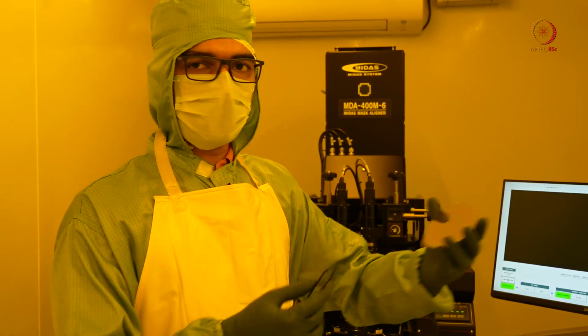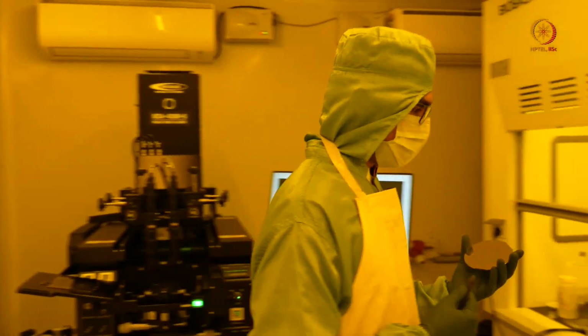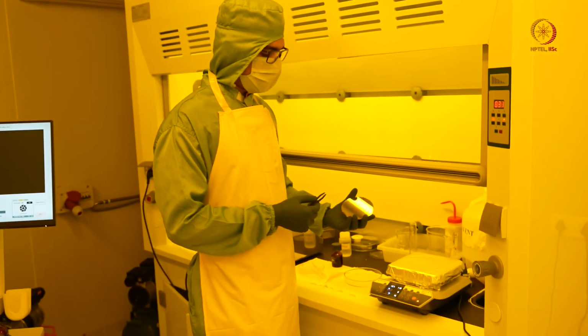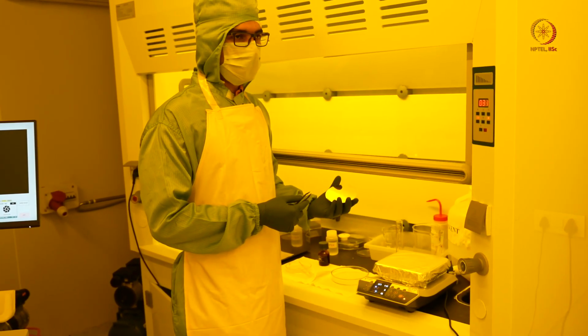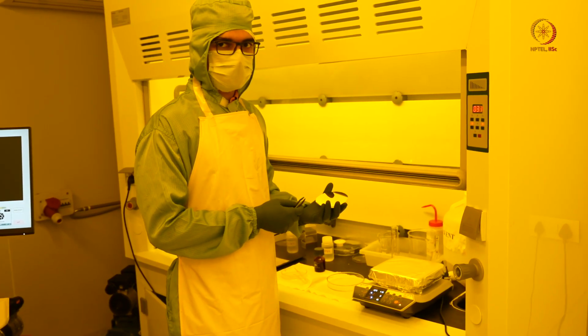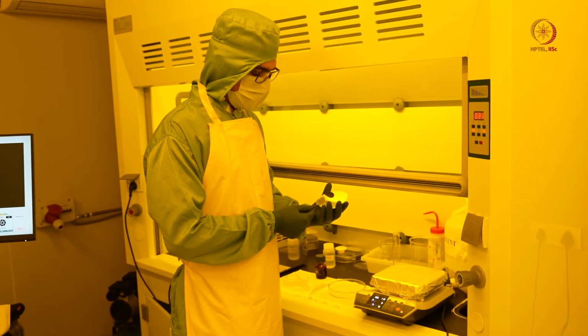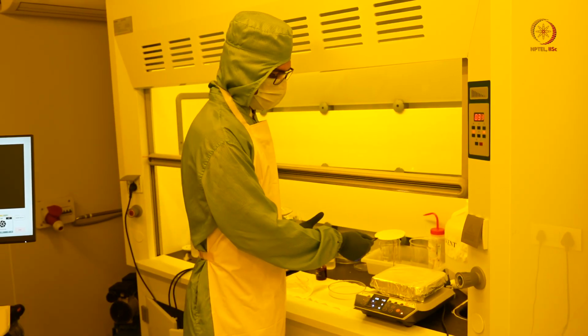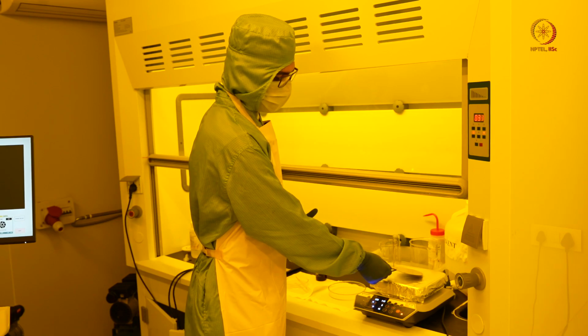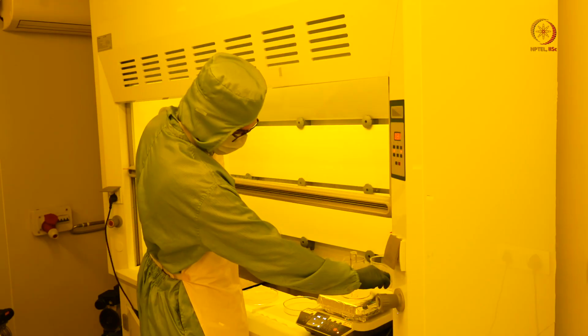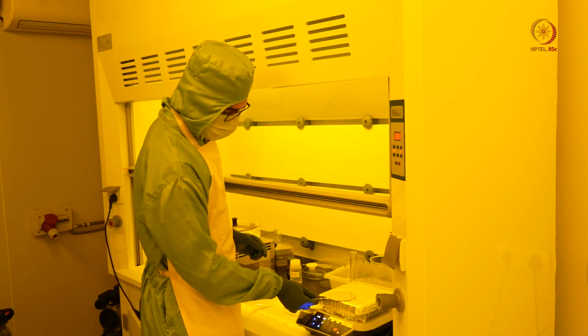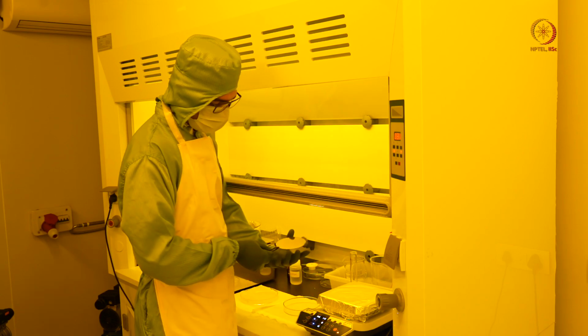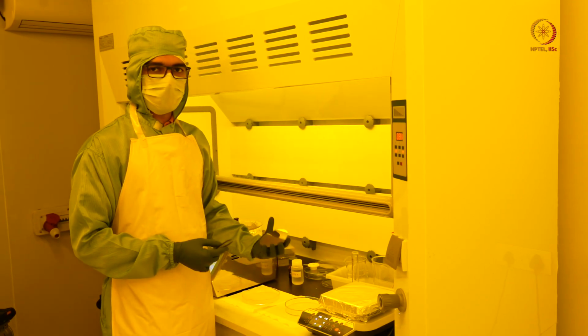So we will again go back to the hot plate. The hot plate is again maintained at 110 degrees Celsius, and we have to do the bake for around 60 seconds again. So I'm loading it. So now I'm removing the sample from the hot plate. 60 seconds is done. And the next step is to do the development process.